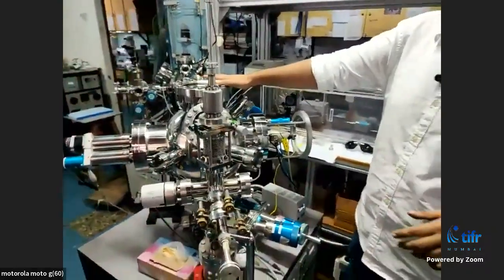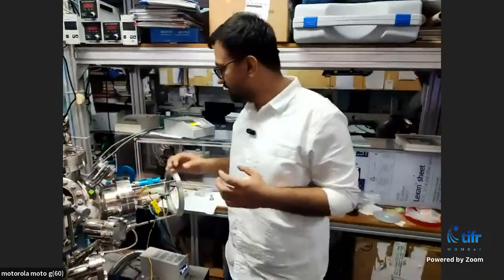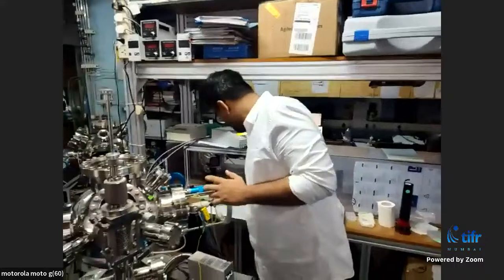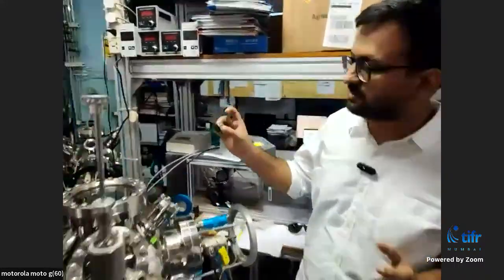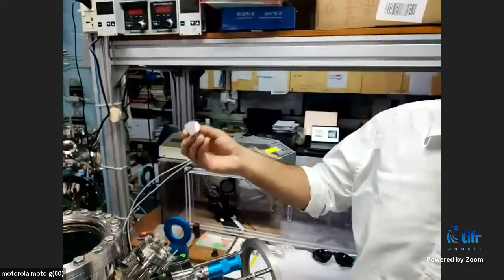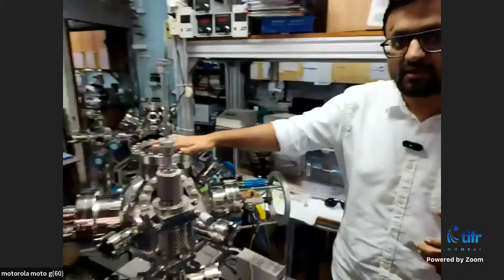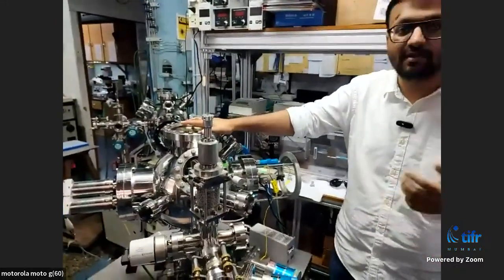where we carry out the deposition process. The main idea behind pulse laser deposition is that you have a target, the material that you want to study. You make a very thick target out of it, and you want to grow thin films. So you bombard that target with this focused laser, and it deposits energy within some top layer of the target, and then the target is ablated out onto your substrate, where you can grow thin films. The target material is stuck on a pellet which is kept inside this vacuum chamber, currently at approximately 10 to the minus 6 millibar pressure.